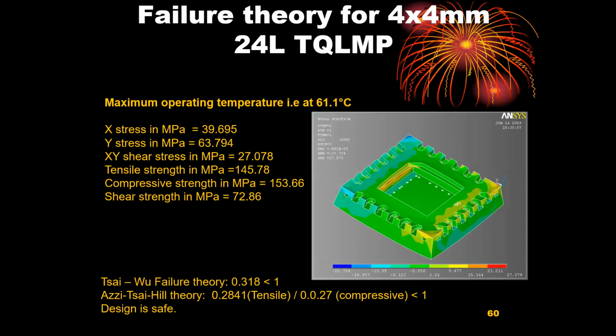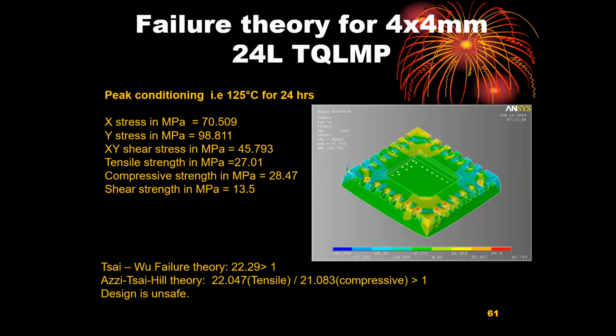Coming to the maximum operating temperature, it was still behaving well. And we had an equation of the left-hand side being much less than the right-hand side. And we were absolutely convinced that it could survive the maximum operating temperature. Coming to the survivability at a peak conditioning temperature of 125 degrees Celsius, which is closer to the glass transition temperature of some of the encapsulants, there was a problem and then it failed. So the survival of it anywhere near the glass transition temperature was a question.